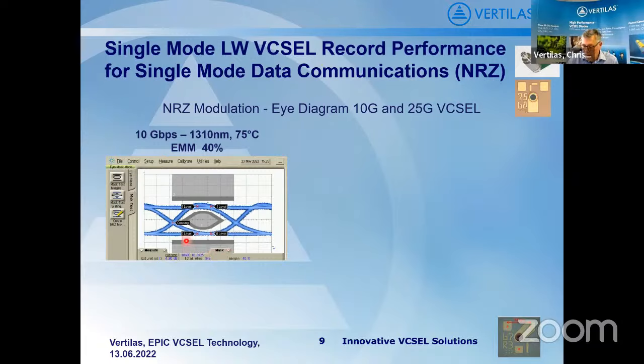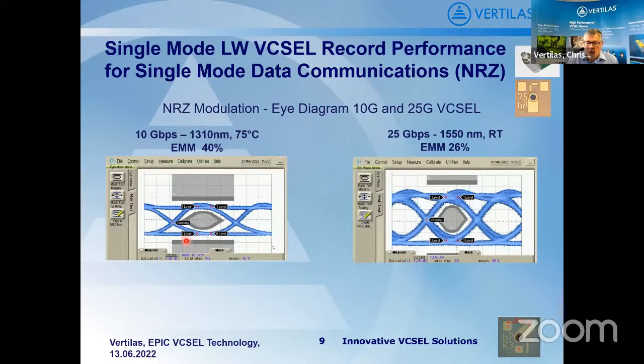and extinction ratio close to 5 dB. We have an even faster product version, which goes up to 25 gigabit NRZ with no equalization. It's a 25 gig laser, which provides a mask margin here of 26%. We have a similar performing laser also for 1310. And for these products, also with equalizer, 50 gigabit NRZ modulation has been demonstrated. Of course, you can go to even higher data rates if you apply DMT or PAM4 modulation.